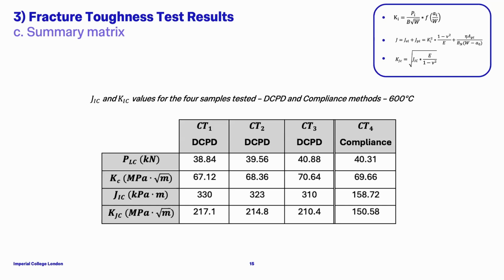Regarding the literature, there were few papers available on high temperature fracture toughness tests at 600 degrees with material as thick as the one I used. They do agree more around this value of JIC, around 300 kilopascal meter. So something went wrong during the experiment using compliance, maybe a misalignment with the clip gauge. It was hard to really follow the test because it was obviously in the furnace. So maybe there was something wrong during the experiment. So we'll just have a look at the three values.